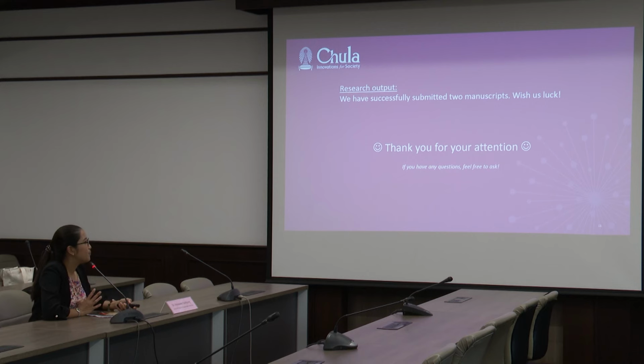We obtain a tensile strength of about 24 megapascals. The key takeaway from this work is that higher additive content increases conductivity and enhances lithium cycling, and cellulose nanofiber can increase the tensile strength, which helps inhibit dendrite growth and prolong battery life. And the output of this work is that we have successfully submitted two manuscripts. Thank you for your attention.